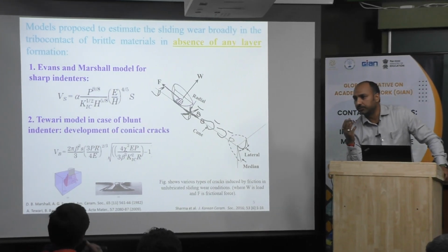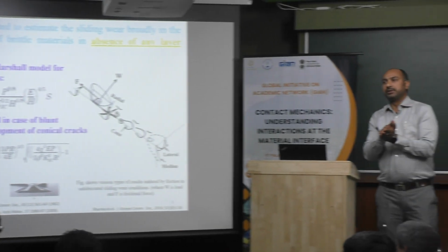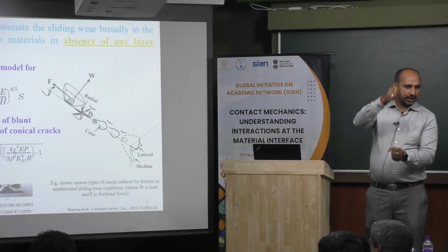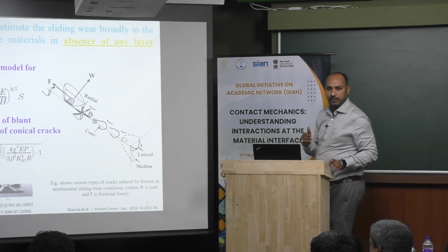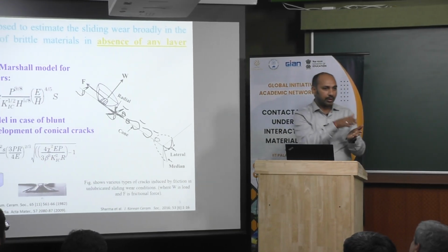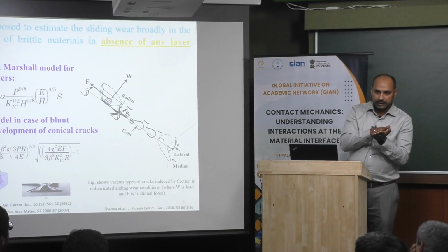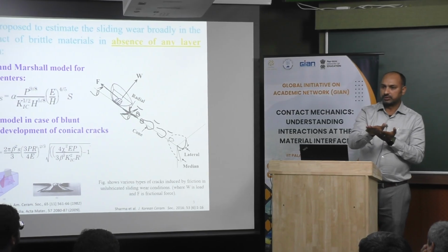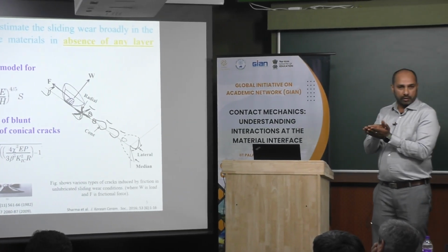K1C means mode one, because ceramic is fractured easily in tensile mode. So when we talk about wear of ceramic, till now we have been considering K2C, because it is metal. Once you consider metal, it gets sheared off easily. In shear mode they can get cut out easily.